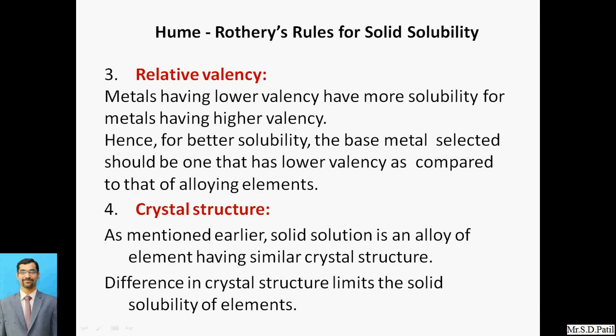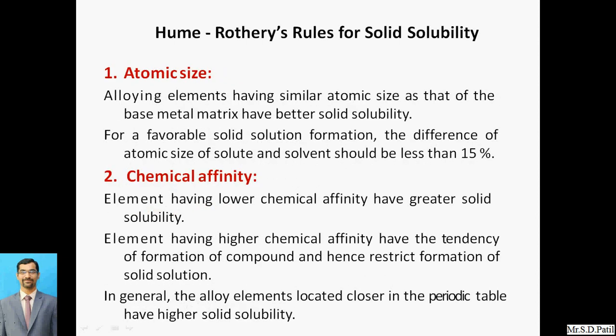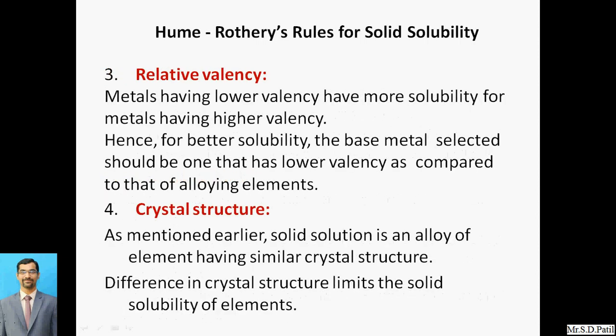The fourth rule is the crystal structure. As mentioned earlier, a solid solution is an alloy of elements having a similar crystal structure. In the first rule, atomic size, we also talked about the crystal structure. Both should have the same kind of crystal structure just to achieve good solid solubility. The difference in crystal structure limits the solid solubility of elements.